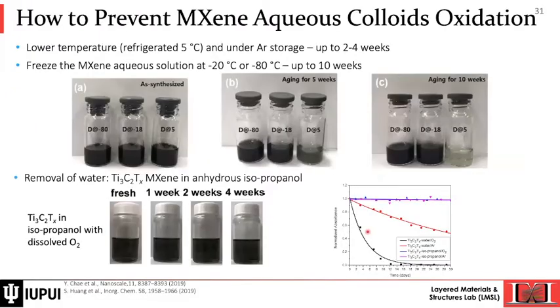The next way to protect MXene is to freeze the MXene aqueous solution. This is another study published in 2019 that clearly showed that if you store MXene solution, you freeze it either in a regular freezer, minus 18, 20 degrees Celsius, or you use a minus 80 degrees Celsius freezer. You can keep MXene almost stable up to 5 weeks or 10 weeks. Here you see the MXene in the fridge at 5C, that almost everything turned to oxide. And here you can see that these that were kept in a freezer were both stable.